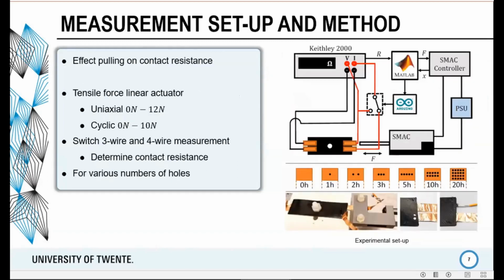For the measurement method, we wanted to see how robust the contacts are. And for this, we simply pull on the wire to see if it works. So we have our sample, which we fix through the hole in the center. We pull on one of the contacts with a linear actuator, and we did tests with uniaxial pulling, going from 0 to 12 newtons step by step.